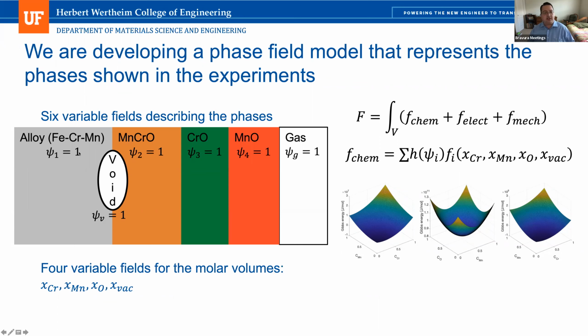And so we have 6 variables representing all the different types of regions of the material that we might have. So we have our 4 phases, and also we have a void phase, and then we have the gas phase where we have the free surface. And so we have 6 variables representing the evolution of those. We also have 4 additional variables describing the molar volumes of chrome, manganese, oxygen, and vacancies.